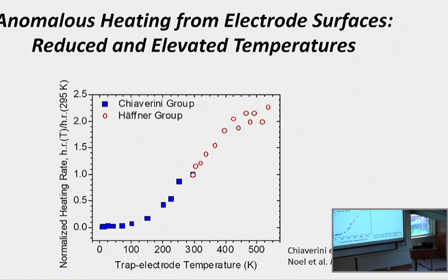Well, to surface scientists that like to study surface diffusion, it looks like an Arrhenius curve, and I can fit that, and it fits pretty well. So it sort of hints at the fact that there's some movement on the surface that's activated, thermally driven or otherwise.